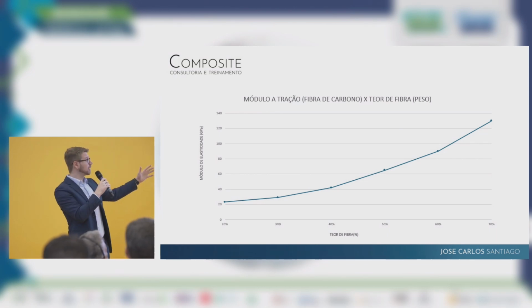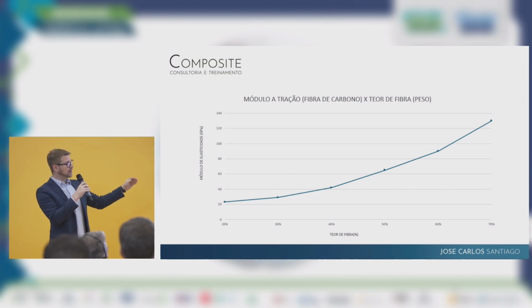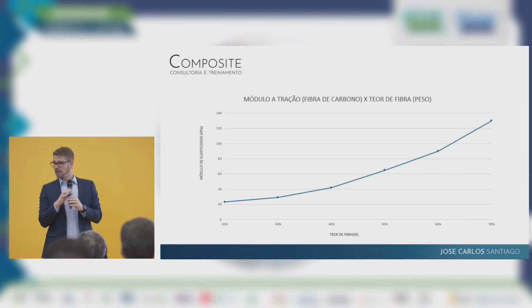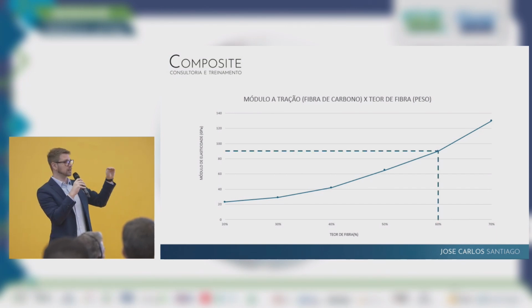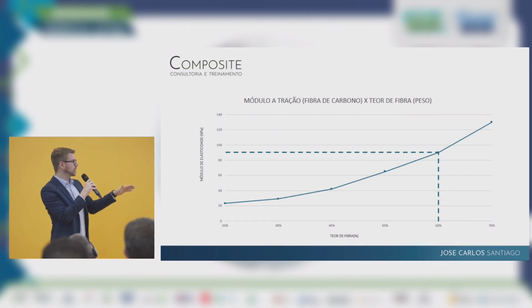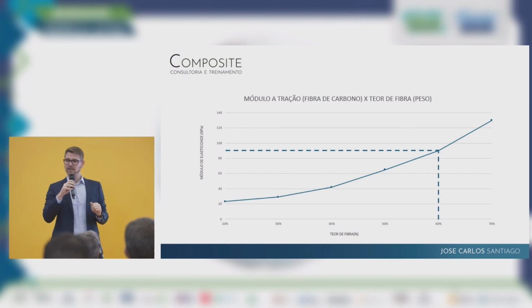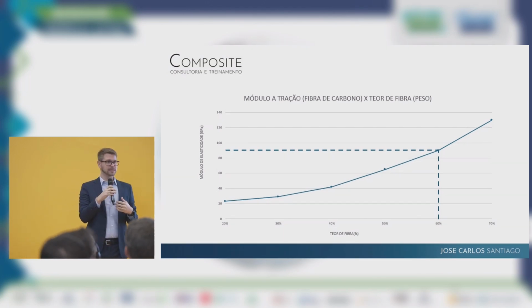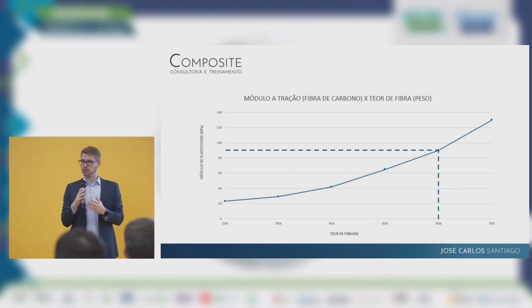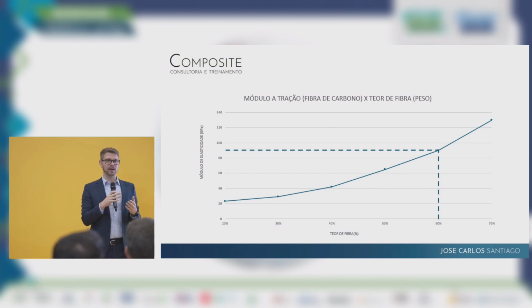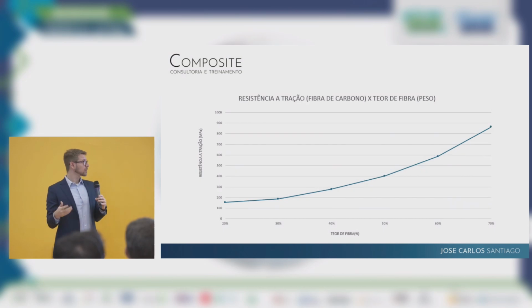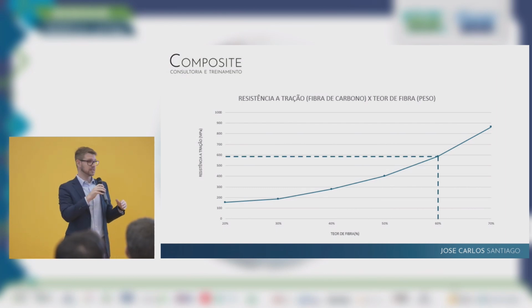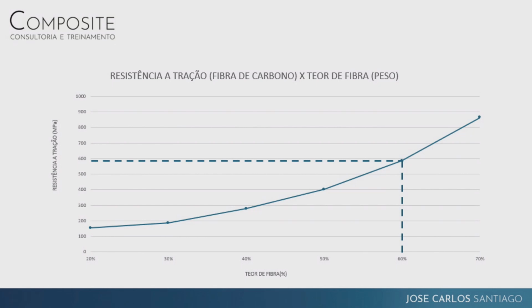And why is that important? Because when we look at the elasticity modulus, the more we increase the content of fiber, the more strength you have. So when we are at 60% with infusion, we have a modulus around 90 gigapascal. Whereas if we had a manual one around 40%, we would be around 40 to 50 gigapascal. Even using a very strong material, if we don't have a compatible construction process, we won't be able to extract all the performance from the material, and also the tensile strength to be around 590. If we had a manual laminate, we would be less than 300.